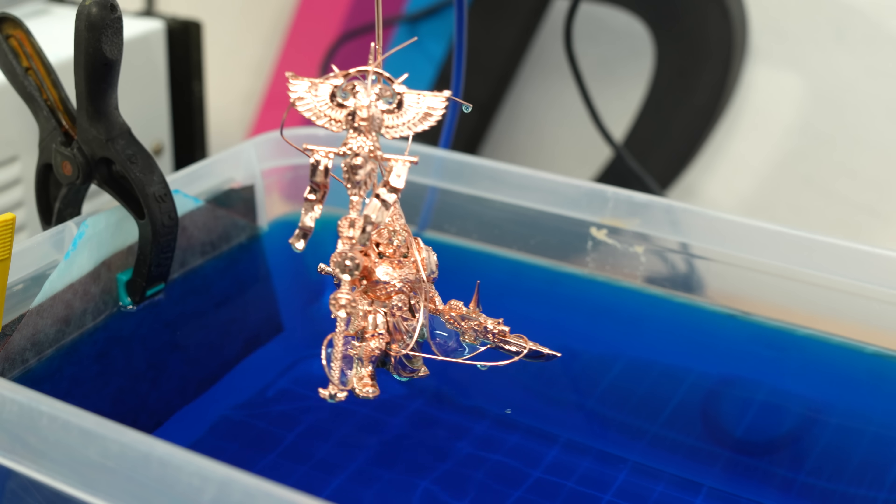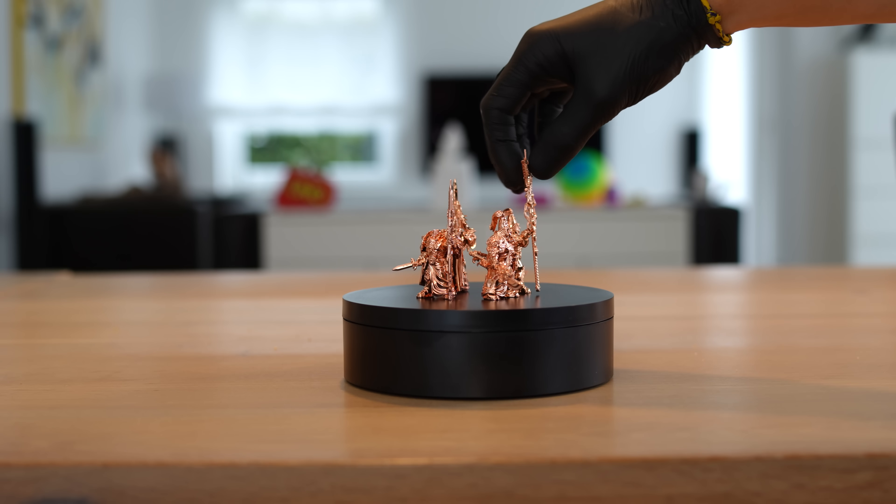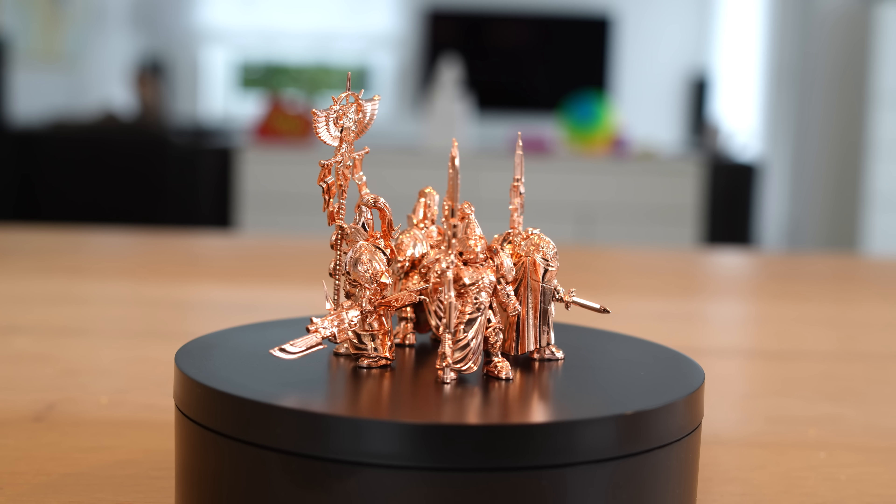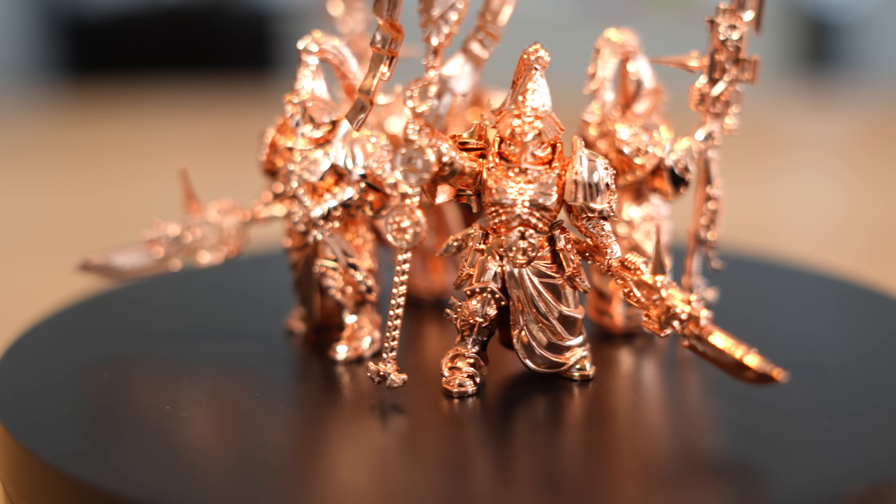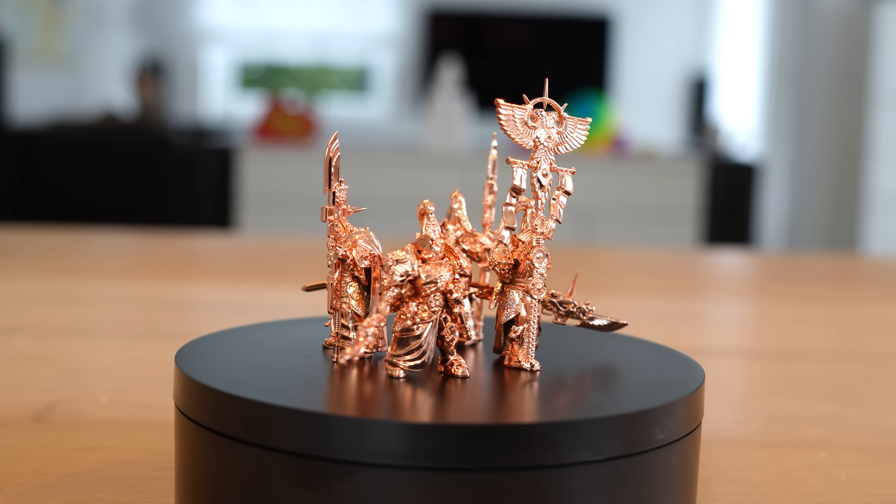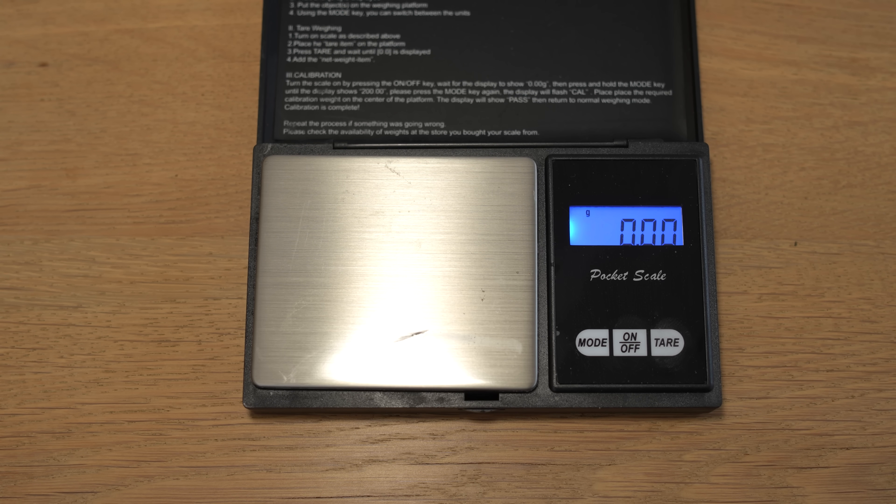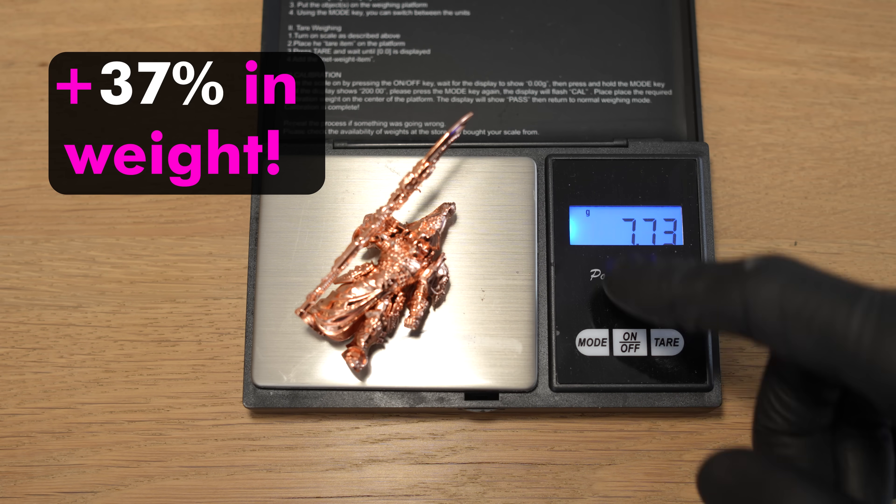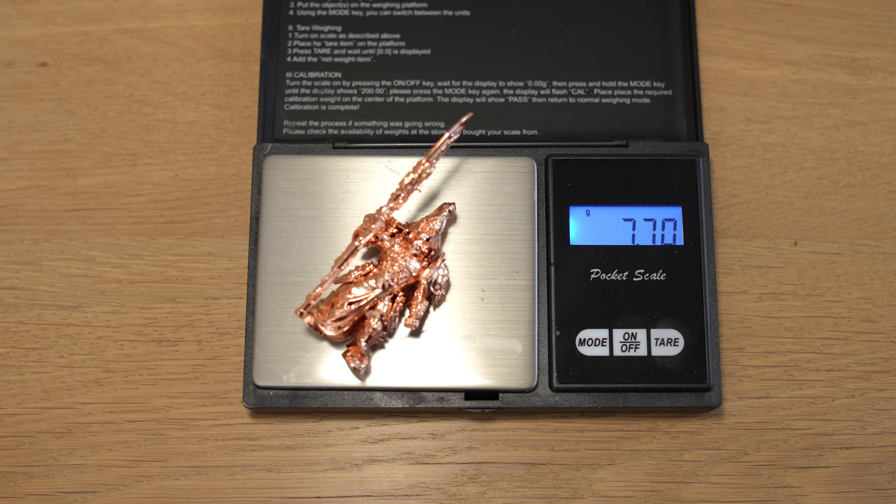Generally, I didn't need any buffing here. The gloss additive in my electrolyte and the even lacquer layer made it possible. You could almost leave it as it is, right? Well, if you ever need a copper base. Any ideas? I go ahead and weigh it. 7.7 grams. That's a 37% weight increase. And you can definitely feel it.